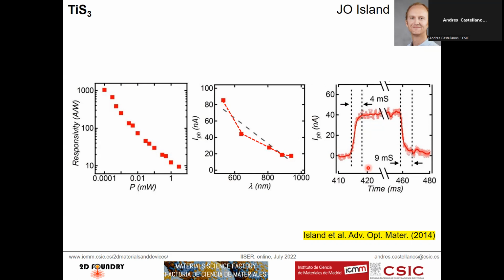That is exactly the reason. Mobility is larger and resistivity is lower than molybdenum disulfide. So the drifting time is much smaller in titanium trisulfide. So you can get similar gain with lower trapping time.